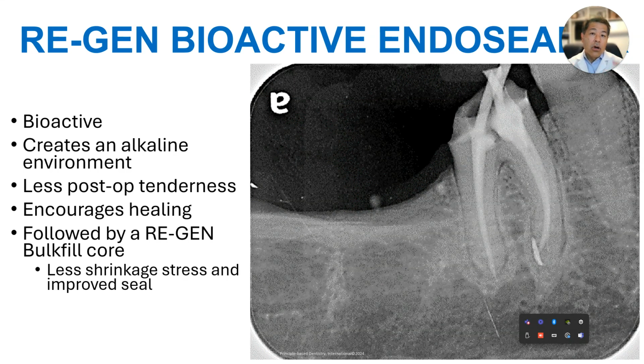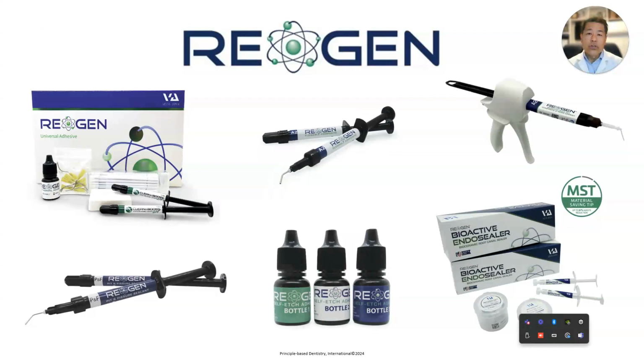Because when I place a large bulk of material, we know we get that volumetric shrinkage. And some of the research shows that if I get a very good bond to the tooth and my core material shrinks, you can actually put stress on that periapical tooth structure in that area. But the bulk fill material is allowed to set and cure, and we're not activating that with a light. With a light, we also have to worry about the penetration of our light. But with this material, we'll have less shrinkage stress.